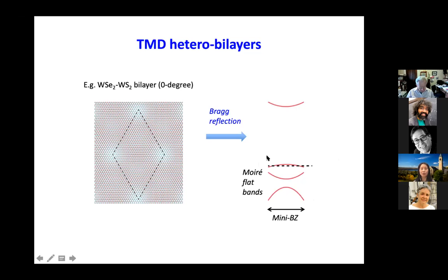And there will always be a mechanism to break the degeneracy here. Now we have an isolated mini band. And this is the band we are going to study. And this is the band that will show a lot of strong interaction effects. And this happens for both electron bands and also for hole bands. And we can tune the Fermi energy, as I said, in a capacitor by applying gate voltage, tune the Fermi level up and down. Then you can dope the material with a certain number of electrons or holes.